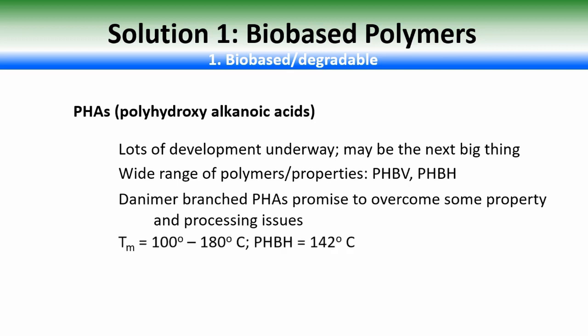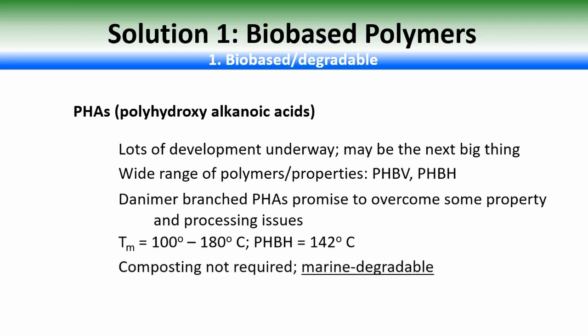Melt temperatures for PHAs range from about 100 centigrade to about 180. The melt temperature for PHBH is 142 degrees, which is between the melt temperatures of polyethylene and polypropylene. Unlike PLA, composting is not required for these polymers. They are spontaneously biodegradable. This is not all positive, as it introduces some durability concerns depending on the application. But most intriguingly for PHBH in particular is that this means the polymer is marine degradable.